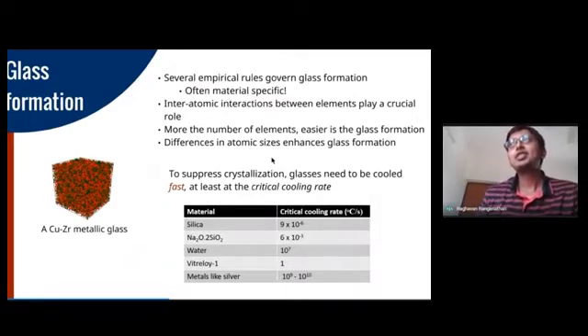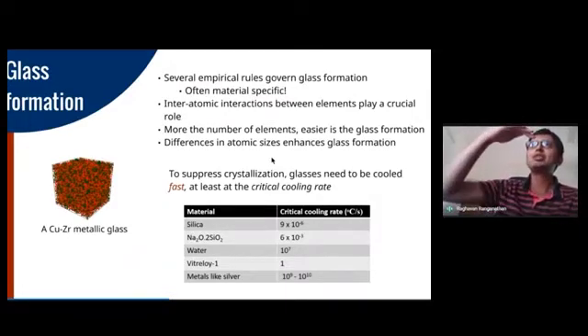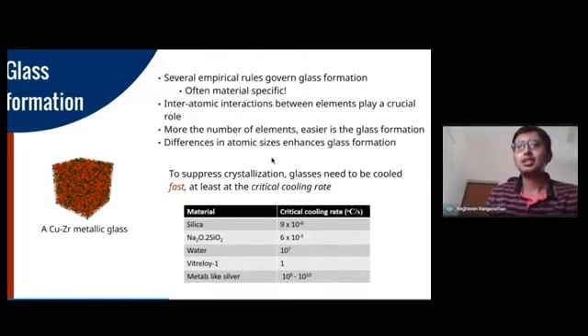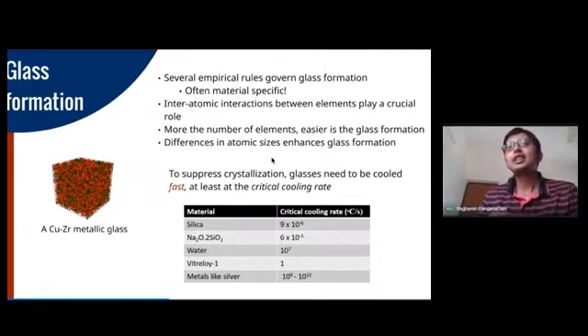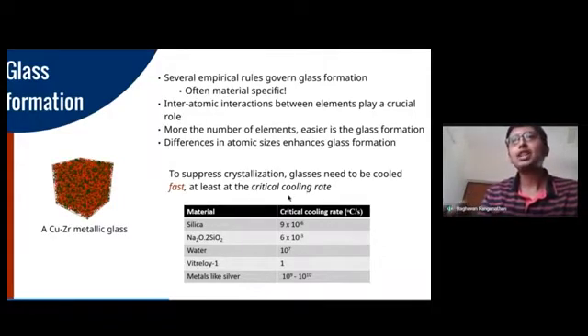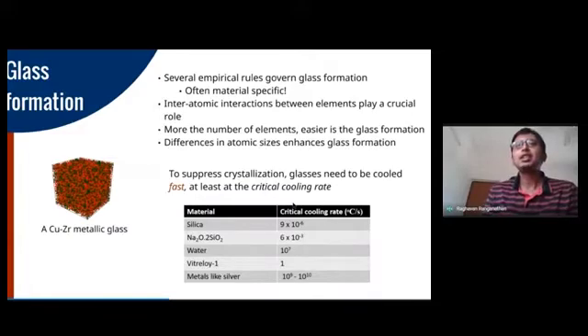Note that what we just discussed is you need to cool this liquid phase at a very rapid time scale, meaning you need to quench it really fast. And there exists what's called a critical cooling rate for all these materials to form glasses. If you take a look at the numbers that I've shown here, silica, we know, is a very good glass former that just requires a cooling rate of about 10 power minus 6 Celsius per second. So that's a very gentle cooling rate.